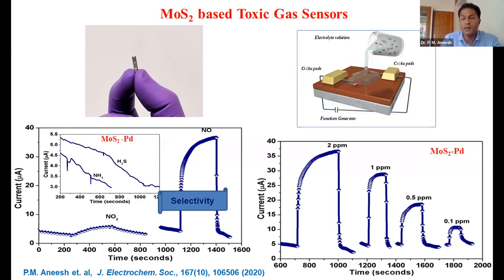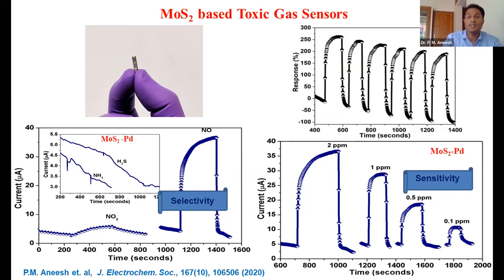And later we checked the sensitivity. So we varied the concentration of these NO gases in different ways, and we found that the current is decreasing with a decrease in the concentration. And that tells you the sensitivity of the devices. And another thing is that we checked the performance of the devices at different intervals also, and we are getting almost similar performance, so that gives you the stability of the devices. So this is one of the devices we fabricated in the lab, and this work we have published in the Journal of the Electrochemical Society in 2020.